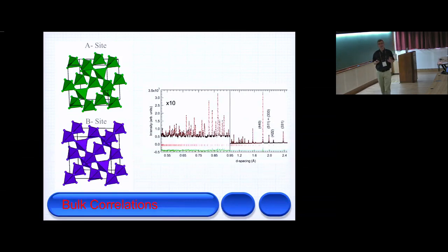on average. And it's become very clear in the pyrochlore structure that at the local level, it's not so beautiful in most of the pyrochlores that we've studied. You'll see that first showing up in the literature because Professor X says it orders and Professor Y says it doesn't, and the transition temperatures might change. But it can be as dramatic as doesn't order at all, a quantum spin liquid if you want, and an antiferromagnet with transition at 1 Kelvin, just by some sample dependence.